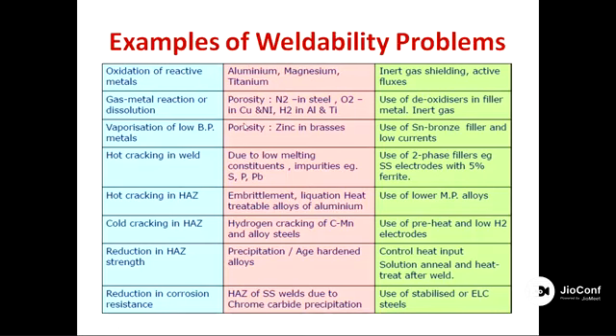Then gas metal reactions will also take place because of some poor shielding or poor welding positions. The nitrogen, oxygen, or hydrogen gases from the atmosphere quickly react with the molten metal. So it gives a defect like porosity in steel, oxide porosity in copper and nickel, and hydrogen porosity in aluminum and titanium. So the filler metal or the welding consumables make use of the deoxidizer.